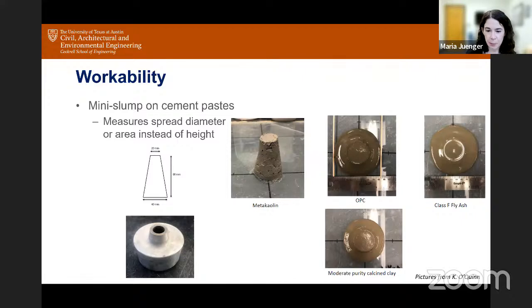And if you replace Portland cement with a relatively pure metakaolin, you get a very, very low slump, which is expected. Compared to the Portland cement shown here, a class F fly ash has a greater slump spread. We measure the spread, not the height, generally in these mixtures. And then this sort of moderate purity calcined clay, something similar to this 77% amorphous material, ends up having a mini slump spread very similar to Portland cement. So you are moderating this problem with workability by reducing the purity. So that's promising.